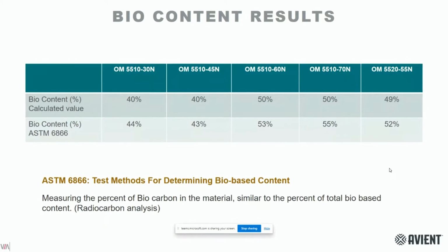We have also measured the bio content within our formulations in order to compare the theoretical bio content we establish in our production against the real value of bio content in our materials. For that, we have performed this ASTM test in order to measure the biocarbon inside the material. And as you can see, in all cases, we are slightly above the theoretical bio content. So it's more than a theoretical thing, more a declaration. It's a real value of bio content within the materials.